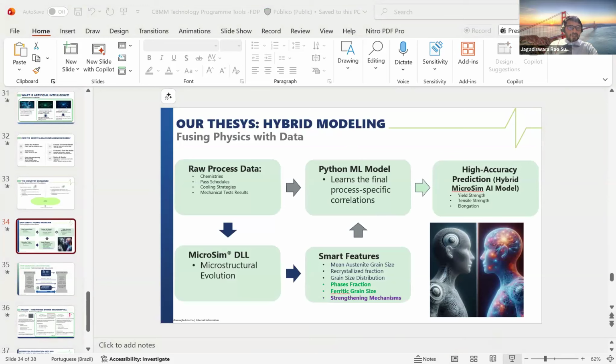So this hybrid modeling is particularly about taking the raw process data, which has the chemistries, pass schedules, cooling strategies, and mechanical test results. I just explained before that we have a microsim model. When the microsimulation model is used for the hybrid model, we call it a DLL model, which gives the microstructural evolution, because it has smart features like the mean austenitic grain size, recrystallized fraction, grain size distribution, phase fractions, and the ferrite grain size.